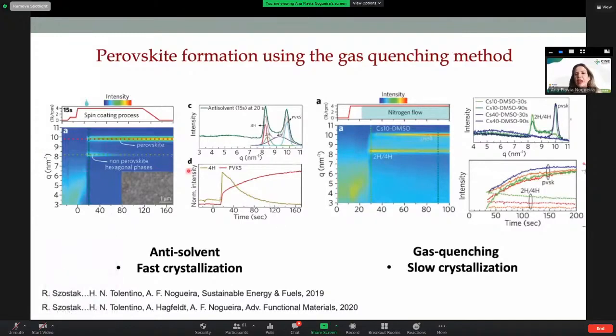But in the case when you have the nitrogen, you can see here that the crystallization is much, much slower. Again, we have the formation first of the hexagonal phases, but until the end of the experiment, we have both the perovskite and the hexagonal phases. This is interesting because if the crystallization is slower, I don't have time to show here, but the grain size is also bigger. And in our record now in Brazil, here in Campinas, we have a record of 22%. This record was made using this method with the nitrogen, where the crystallization is much slower.